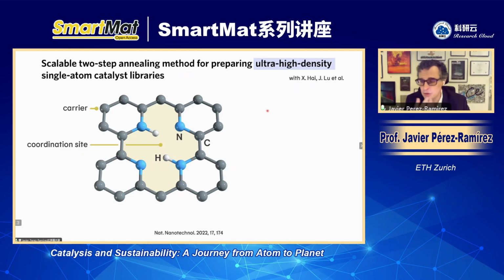So we have worked extensively on approaches to make sure that we increase the metal atom density, but the metal atoms are stable. And I have here an example of one process to prepare what we call ultra high density single atom catalyst. For that, we are using a two-step annealing method. That's how we call it. We developed this together with J. Lu in National University of Singapore back in 2022. This method is widely acclaimed. Many people are using this method these days, so we are very happy about that. Let me show you how this method works.